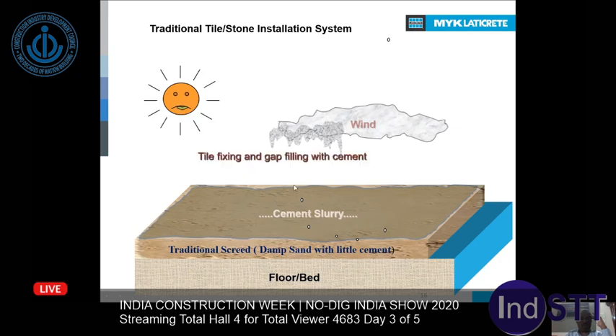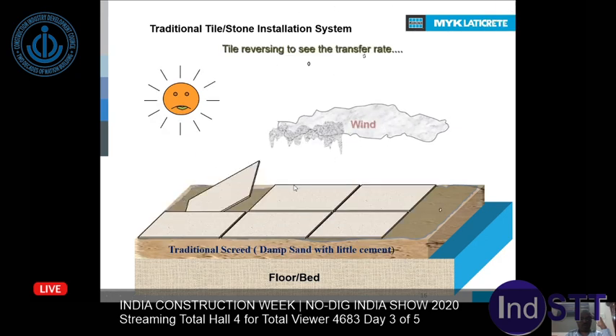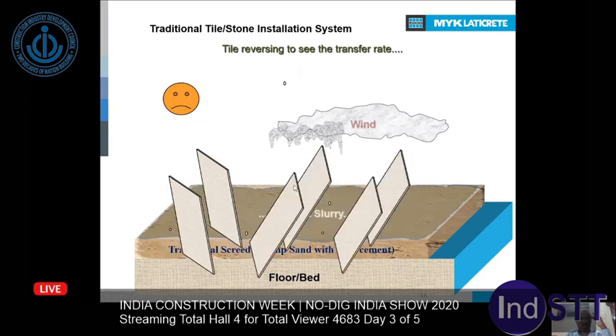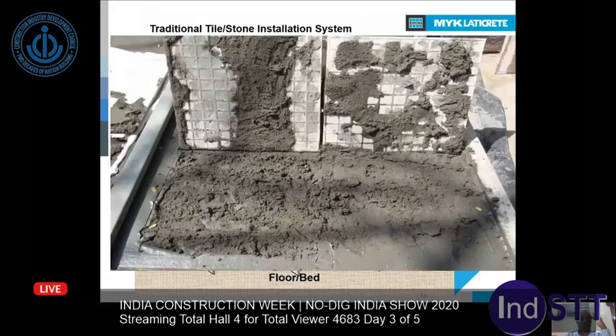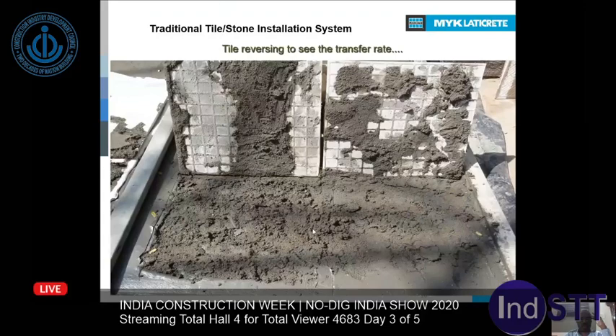The moment you put the slurry, you can see that the cement water is going into the sand bed, and with the hot weather, evaporation is happening. Then the moment you fix a tile over it, you can see that all the water is sucked into the sand bed. Then there is no uniform adhesive coverage on the tiles. You can see that one area has a good amount of coverage, another area has no coverage. So this leads to a hollow sound. And when you put a small amount of stress, in places like airports where you walk, the tiles start cracking.